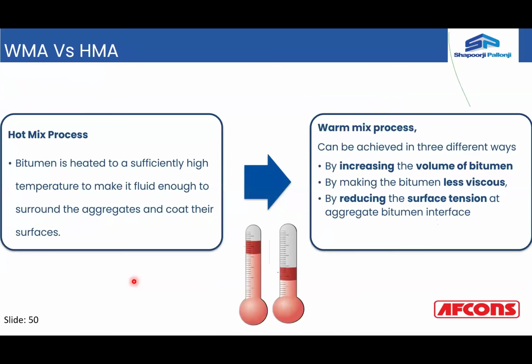If you compare the warm mix asphalt and the hot mix asphalt, generally the bitumen is heated to a sufficiently high temperature to make it fluid enough to surround the aggregate and coat the aggregate surfaces. But in the case of warm mix asphalt, the volume of the bitumen is increased by the additives, making the bitumen less viscous and reducing the surface tension at the aggregate surface and bitumen interface. So basically, the coating ability of the bitumen is enhanced by adding the additives in the mixes.